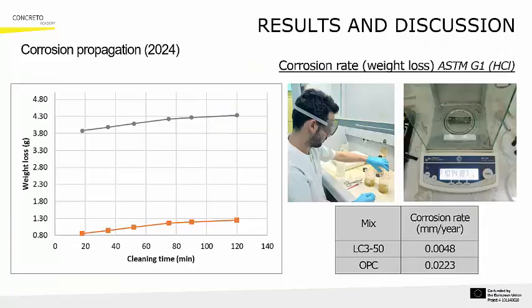To quantify the visual observation, corrosion rate was measured through weight loss analysis following ASTM G1 using hydrochloric acid. After carefully cleaning the rebars to remove corrosion products without damaging the base metal, the mass loss for each sample was calculated. The results were striking.